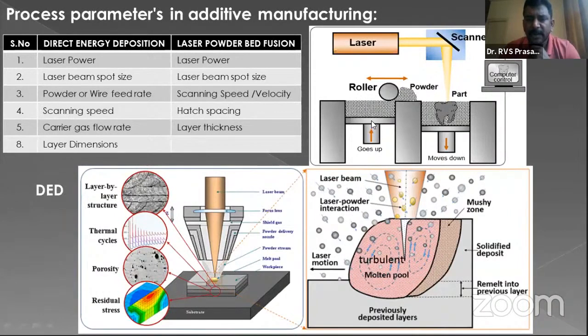One is going up and another is moving down. In powder bed fusion, once one layer of the part is printed, the ram moves down so that the other side goes up and pushes the powder with the help of a powder roller. Then a layer of powder is formed, and the laser beam comes and melts the required regions according to the 3D design you have given as input. Layer by layer it will print, and then you will end up with the final component.